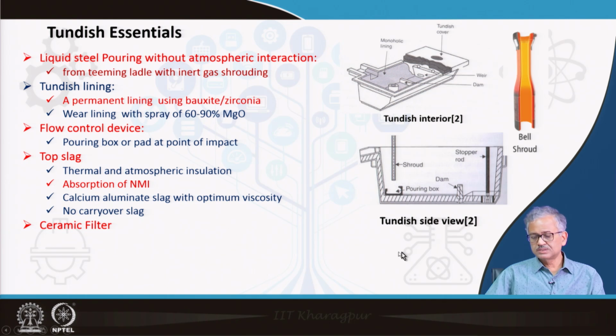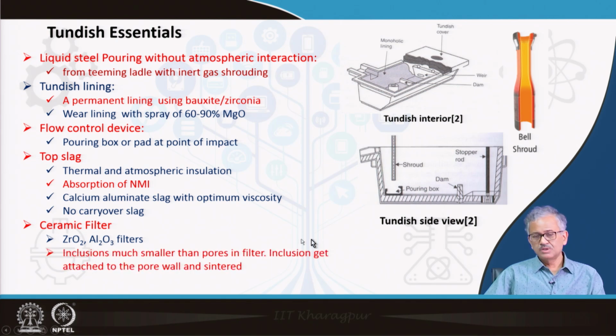Then ceramic filter: you can use a ceramic filter at the tundish exit, and it also basically arrests the inclusions to some extent. The filters usually used are zirconia alumina filters, and they can arrest inclusions, but the inclusion is much smaller compared to the porosity of these filters. So it is not like the usual filtering method where the inclusion will not be allowed to pass through the pores. They can easily pass through the pores, but they get arrested in the filter because the inclusion gets attached to the surface of the pores. Okay. So that is the way. The inclusion is much smaller than the pores in the filter. The inclusion gets attached to the pore wall and gets sintered at high temperature. So that is the way this ceramic filter arrests some amount of inclusions.